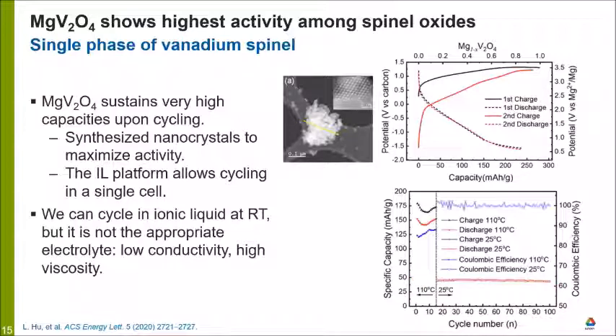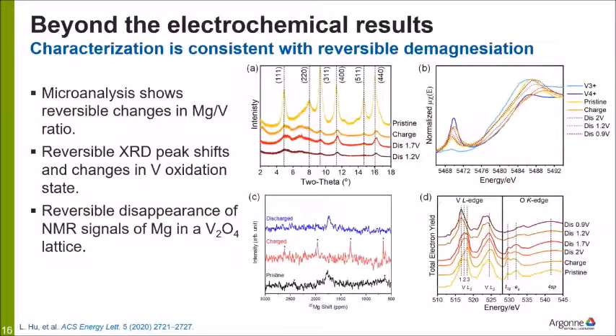But as I said earlier, just looking at the electrochemistry data is certainly not enough. So a complete analysis of this material was completed, to verify reversible magnesium intercalation into the structure. Microanalysis shows that reversible changes in the magnesium vanadium ratio are observed during this process. And then we can also see that reversible XRD peak shifts, as well as reversible shifts in the vanadium oxidation state, were realized.